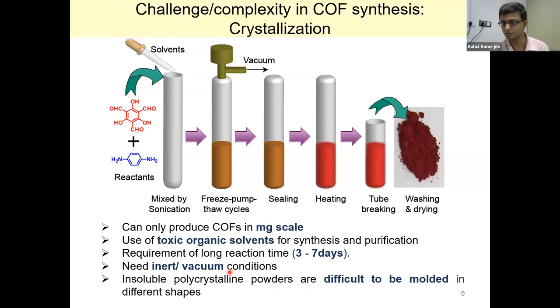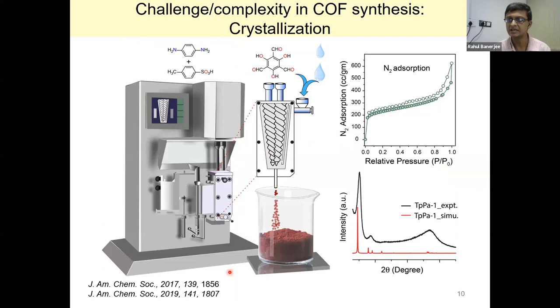You need very inert, high-vacuum conditions, flame sealing, and breaking the seal — it's not really industrially viable or feasible. Once again, with a lot of pleasure, I can say that we could sort out that problem as well, using para-toluenesulfonic acid (PTSA)-based synthesis of these soft materials in our laboratory. My colleagues at National Chemical Laboratory are now using this method and making almost half a kilogram of covalent organic framework material for the Gas Authority of India.